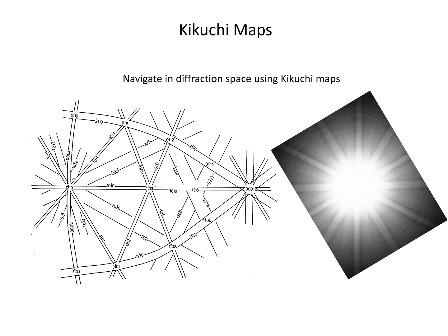We're looking directly down the C-axis. And if we want to move to another orientation, say a prism orientation up here, what we would do in the microscope in real time is tilt the sample so that the orientation changes and moves us up this set of tram lines over here till we get to there.